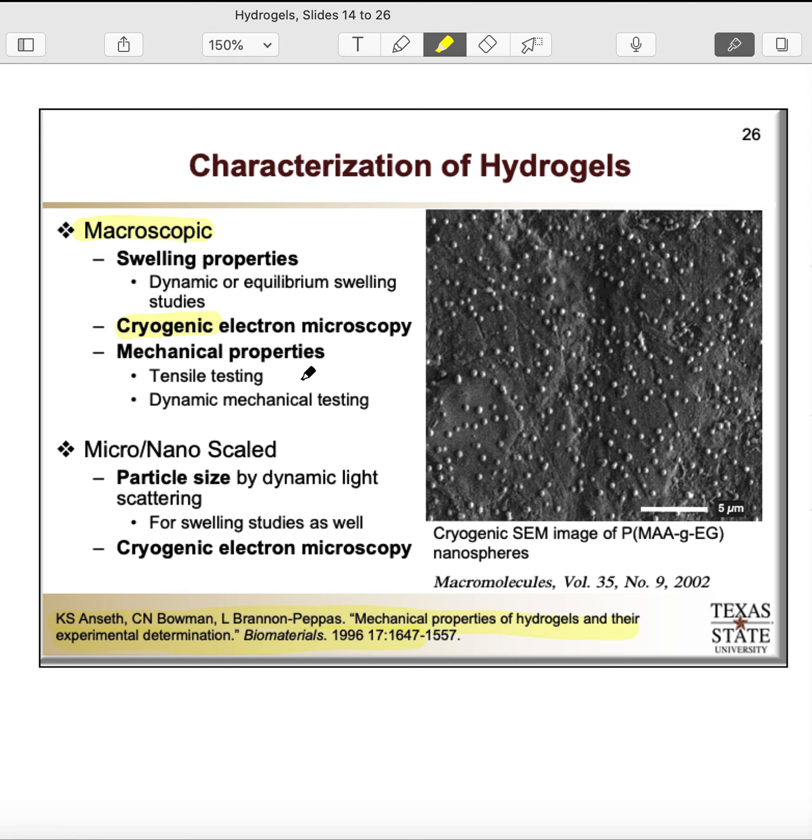One thing that's important is that in any kind of tensile testing or mechanical testing, you do want to maintain the hydrogel in the swollen state, and so drying of the water during the testing can significantly affect the results. So for that reason, as I mentioned, for tensile testing, ideally you would have the sample immersed in water or in buffer while testing. And in this other particular system, since you cannot typically immerse it, what you can do is to try to seal the system utilizing silicone or petroleum grease in order to prevent water loss.